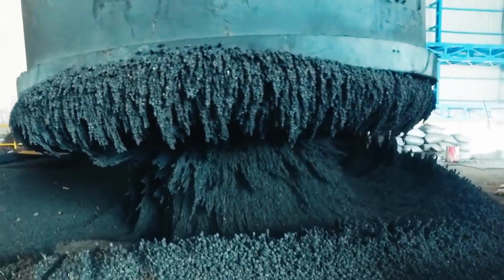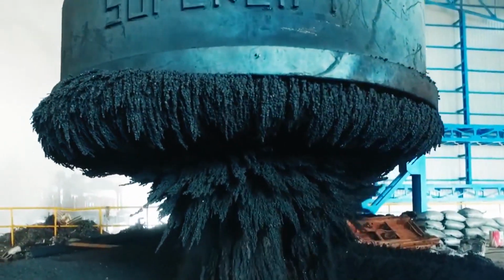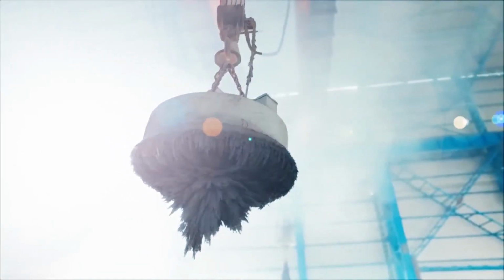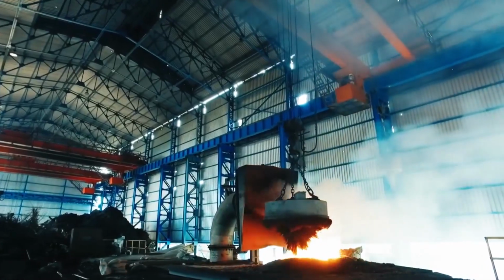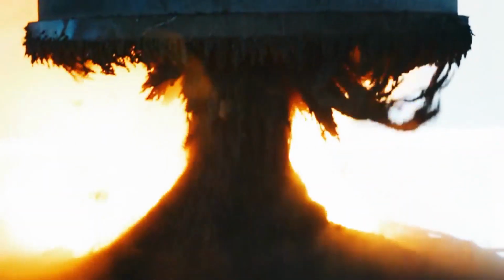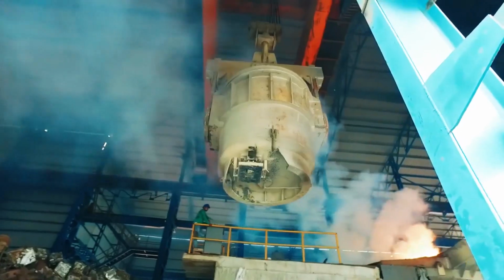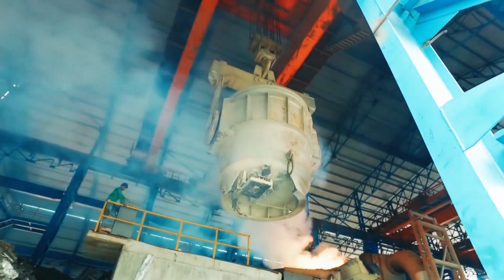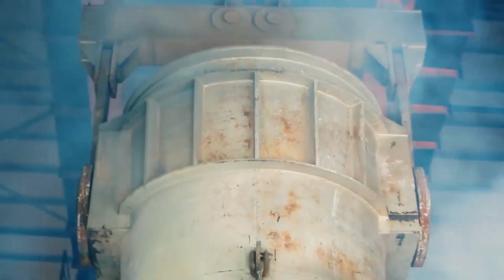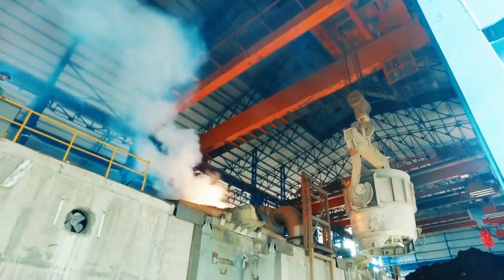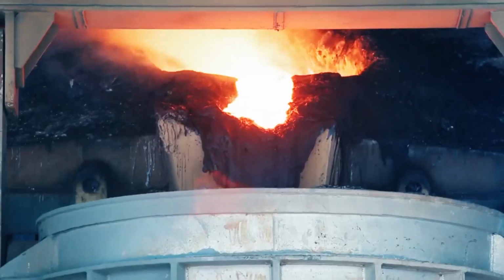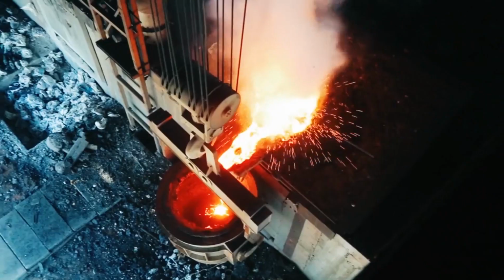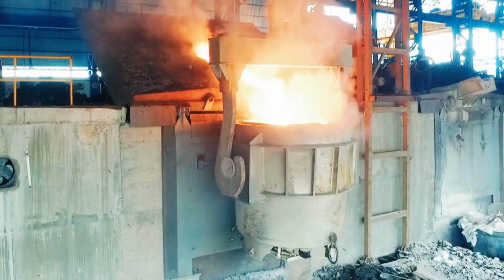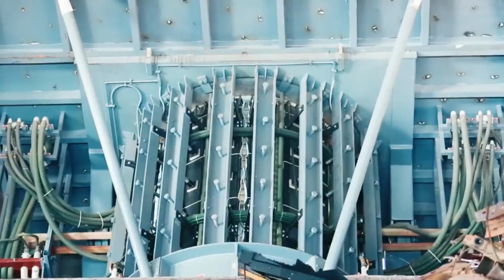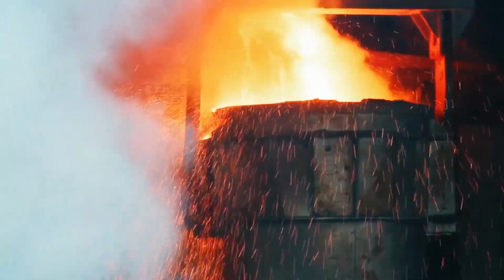Here, directly reduced iron ore, being the raw material, is charged into a 30 metric ton mega furnace, using giant electromagnets for the melting. Once the charging is completed and the desired temperature of 1650 degrees centigrade is achieved, the melting takes place in the coreless induction furnace composed of a refractory container which is surrounded by a helical coil connected to the source of alternate current.